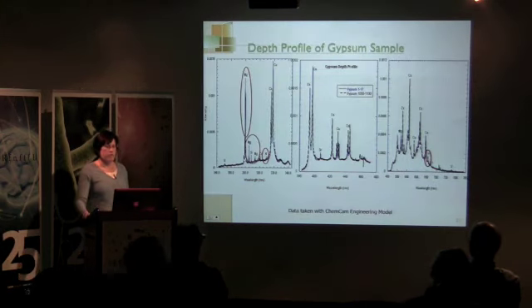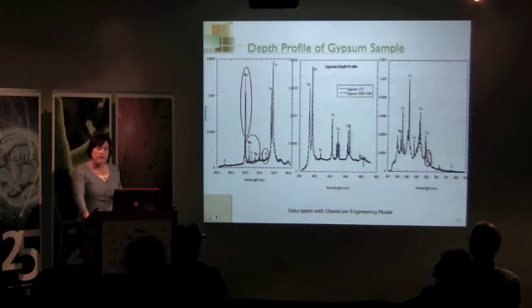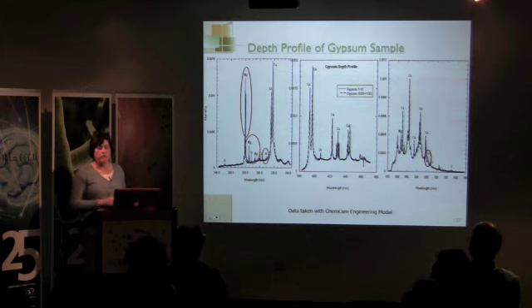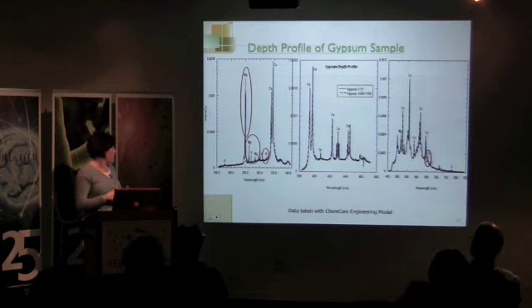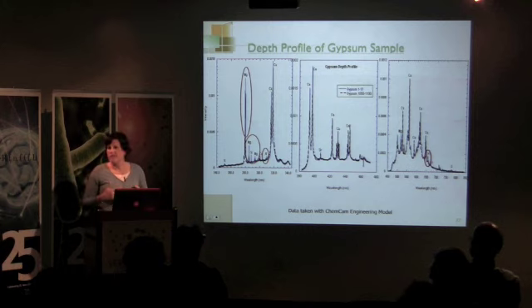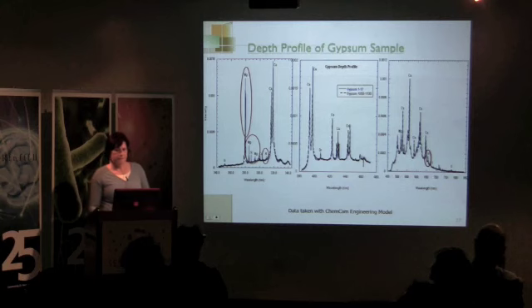Here's a depth profile showing that same gypsum sample, and it might be a little hard to see, but in black and blue, you have 2 different numbers of pulses. The first pulses were in blue, the first 17, and you can see that the spectra changes as you go down to the black one, where we took pulses from a higher number after essentially cleaning off the surface. And so this is just evidence that we'll get a different spectrum if we clean off the surface.